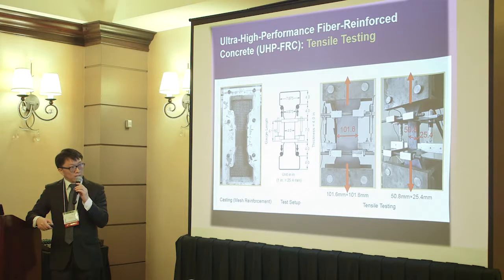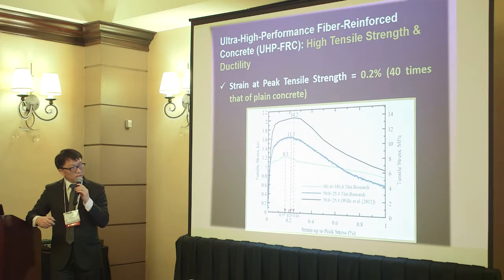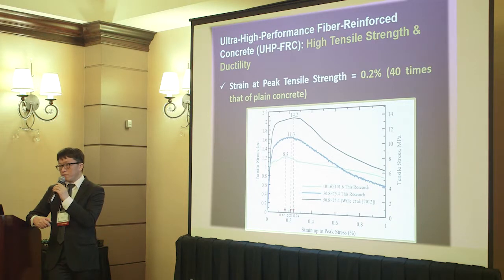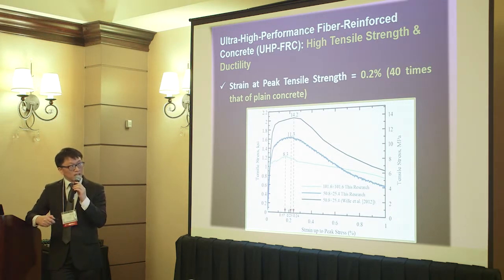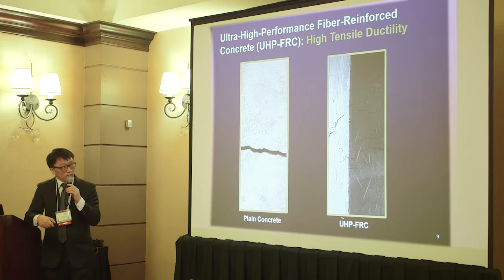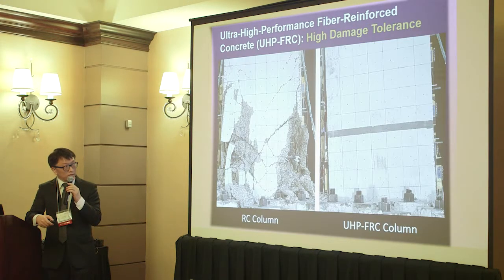And for its tensile capacity, we do direct tensile testing, and you can see there's ductility. It's not like conventional concrete, which fails immediately once it reaches its tensile capacity. This shows a ductile behavior like steel. Its strain at peak is 40 times compared to conventional concrete. It can be stretched a lot without failure. So these are photos comparing plain concrete and UHP-FRC after tension.